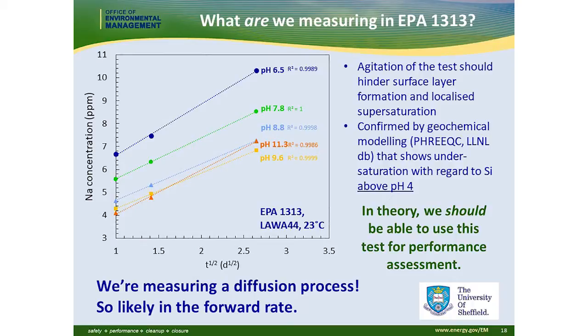The geochemical speciation modeling using PHREEQC and the Lawrence Livermore National Lab database, we used to confirm that as long as we were above pH 4, our test conditions were well below saturation with respect to silica, which means that we're maintaining the expected boundary condition, that being a dilute boundary condition that would again maximize the forward rate in this leaching test.